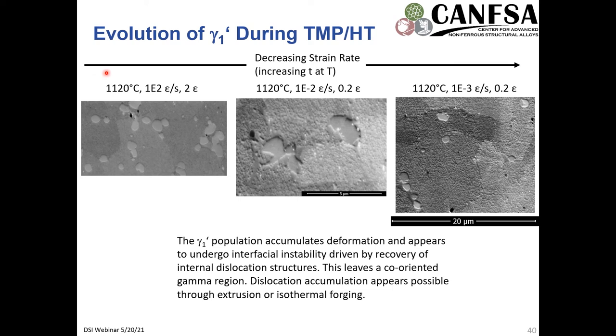One is time at temperature for the evolution of the primary gamma prime, and the other is obviously the strain rate. So on the left we have a very high strain rate, and relatively little evolution of the primary gamma prime. However, at a decrease in strain rate, we have a very disrupted interface of the primary gamma prime. We have this shelling that's still occurring at the expense of the primary gamma prime. And at even longer time at temperature or at lower strain rates with extended deformation, we have a lower phase fraction of the primary gamma prime.